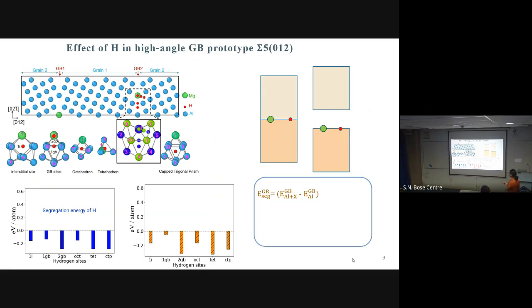Okay, so this blue part corresponds to the hydrogen. This is the segregation energy of hydrogen, and segregation energy of hydrogen means, if there is hydrogen and it migrates to the grain boundary, what is the tendency of the hydrogen, or what is the probability that the hydrogen will go and sit at these interstitial sites? These interstitial sites are named here. And similarly, this is the segregation energy of hydrogen in presence of magnesium. That is, if magnesium is already present, and then we put hydrogen in presence of magnesium, how the effect changes.